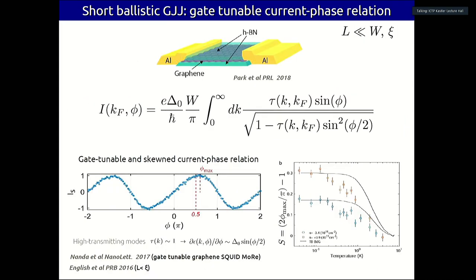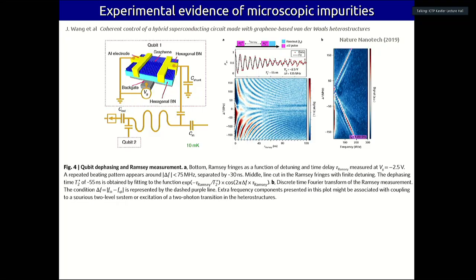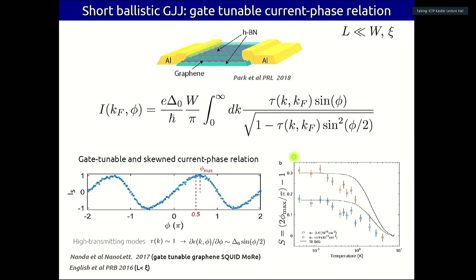These devices have been implemented using very clean interfaces between graphene and superconductors via encapsulating graphene in hexagonal boron nitride, which allows one-dimensional edge contact. This setup has allowed measurement of the current-phase relation, which has a characteristic non-sinusoidal behavior, unlike Josephson tunnel junctions. This skewness is tunable via the gate voltage, and it depends on temperature. The overall qualitative trend is predicted by the Titov-Beenakker-Bogoliubov-de Gennes approach, but it is quantitatively not in perfect agreement.